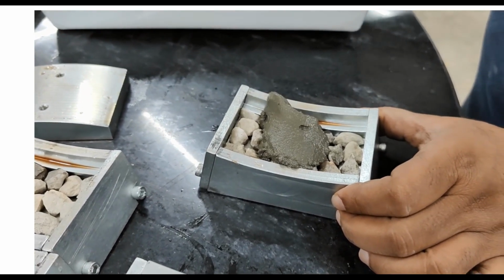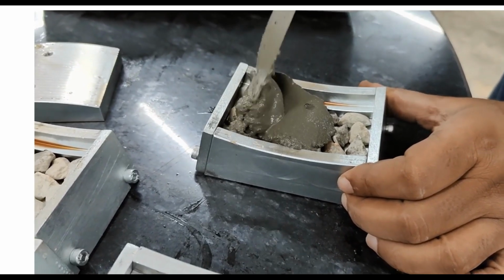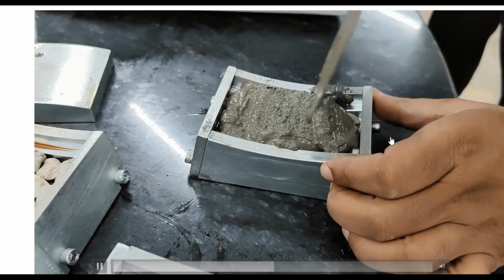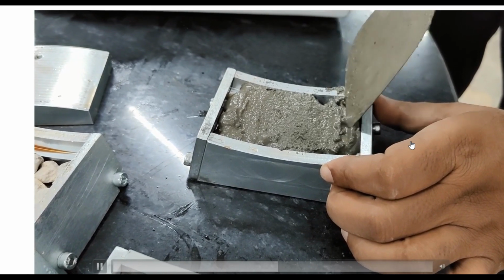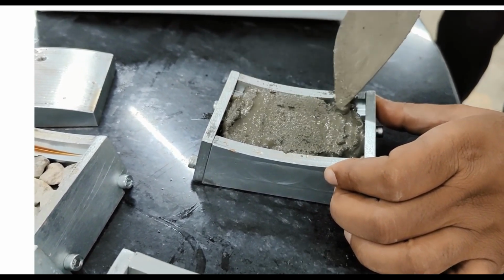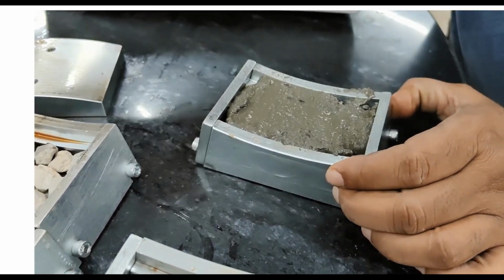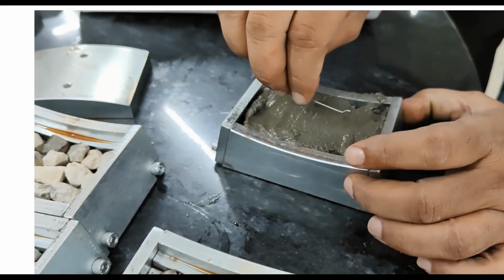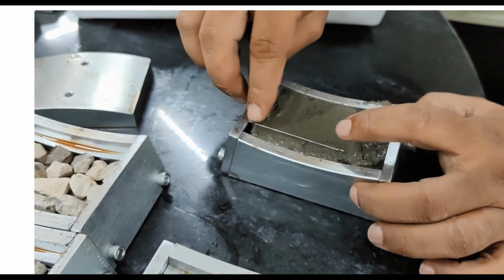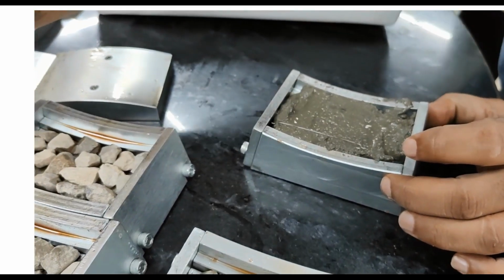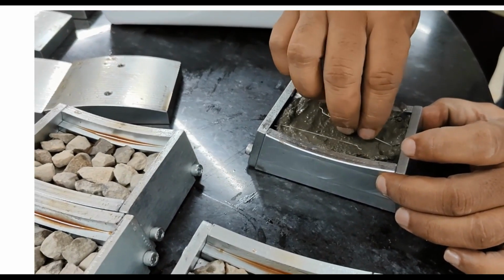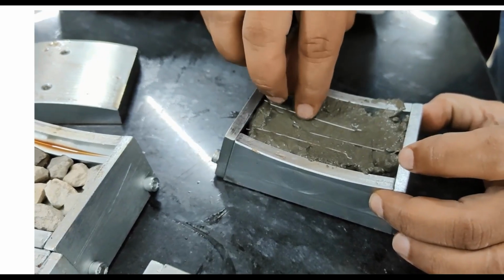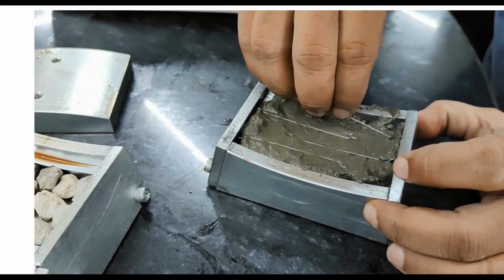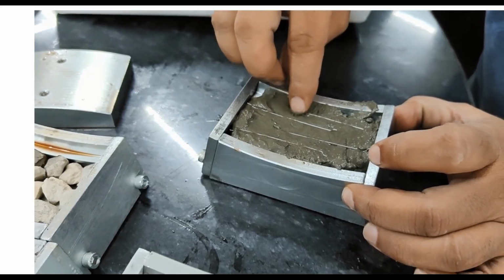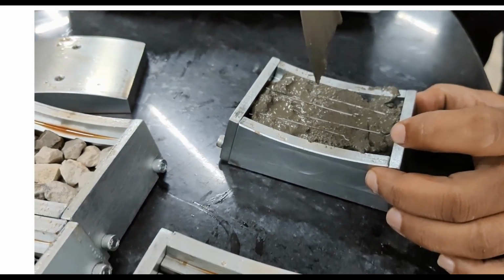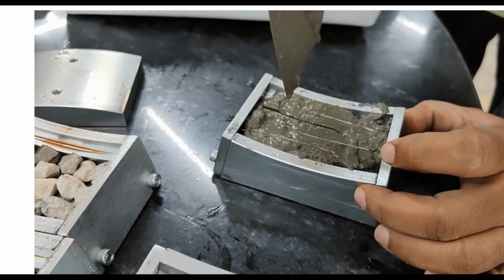Place the paste carefully on the surface of the mold and do not tap the specimen. Otherwise, the cement paste will go below the aggregate. Now place 3 to 4 pieces of reinforcement, 1.2 millimeter wire, laid along the longer dimension, and just push these wires in with the spatula.